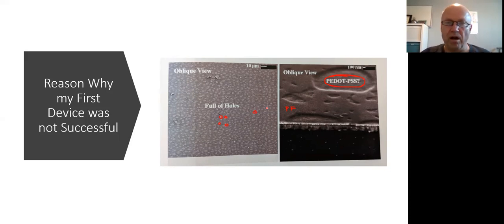To make a long story short, I eventually realized that the solvent I was using for spin coating had a minor trace of water in it. So I had to do distillation and get rid of all the water out of the solvent. And then in the end, I was able to make these nice smooth films. My theory was that the water droplets were not evaporating as fast as the solvent, so these are imprints of water where the polymer couldn't coat in various spots. So this is an SEM image.